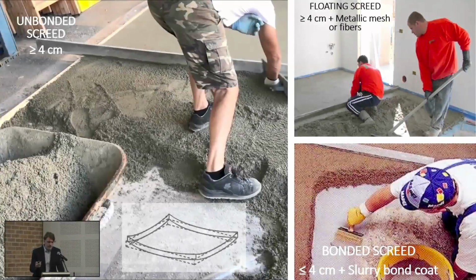Okay, these are some examples of a screed that can be done in the job site. All of them have their specification to be done, because the layer of cement cannot be just done 2, 3, 4, 5 centimeters; you must respect the regulation about the screed. Just to give you an example here, we are doing a screed of 3 centimeters, but before doing this, we need to apply a slurry bond coat on the surface. Otherwise, we have this effect.